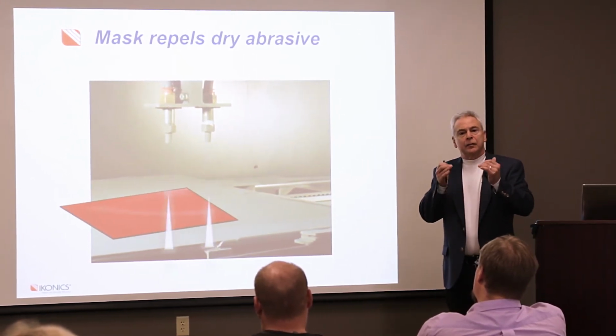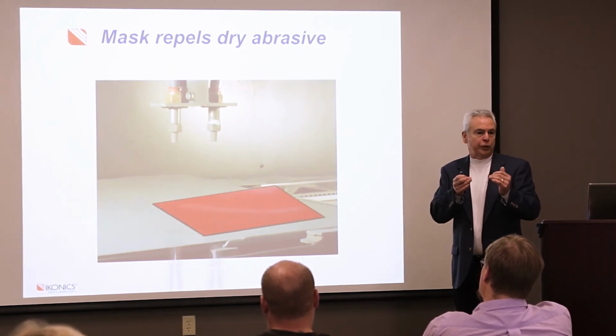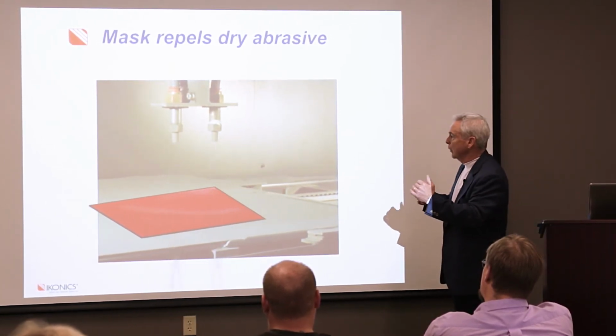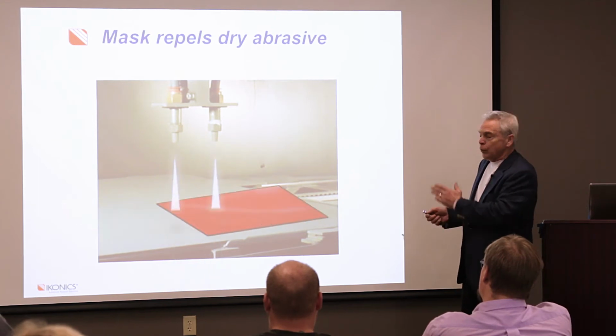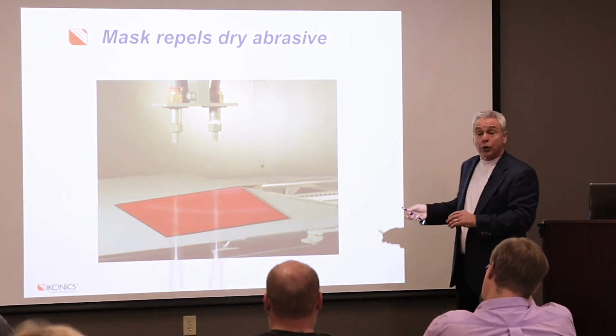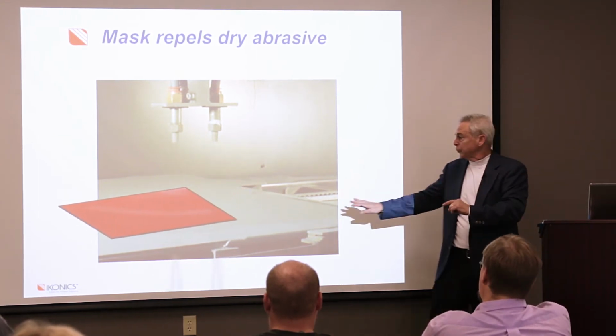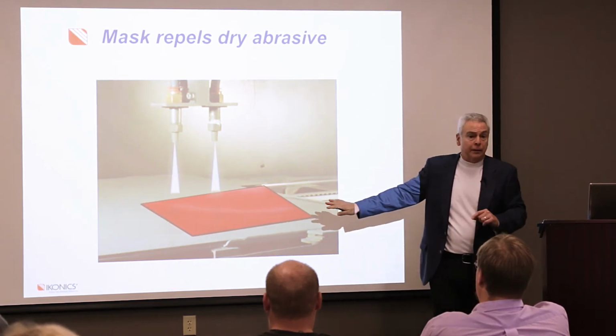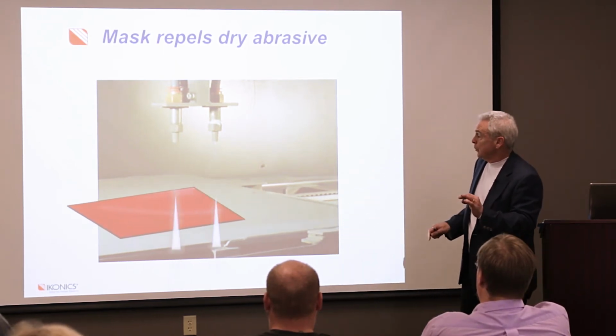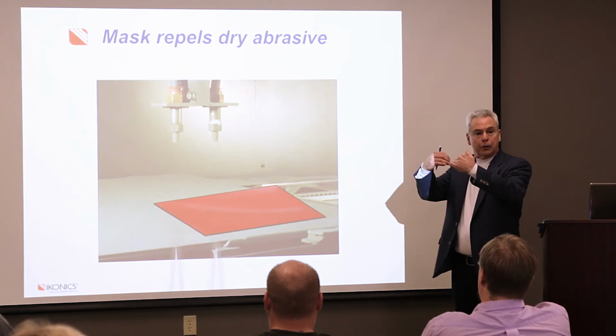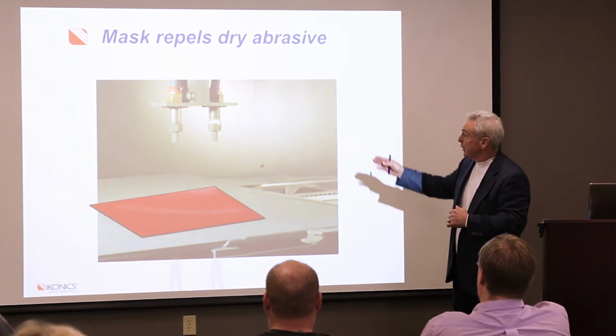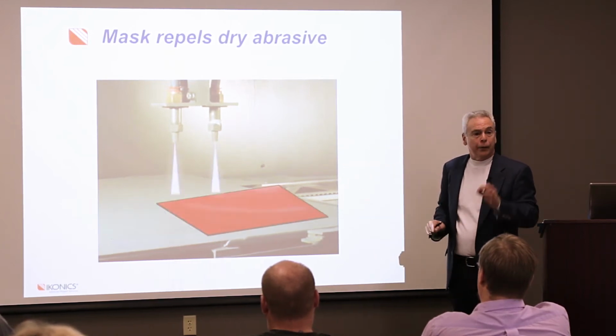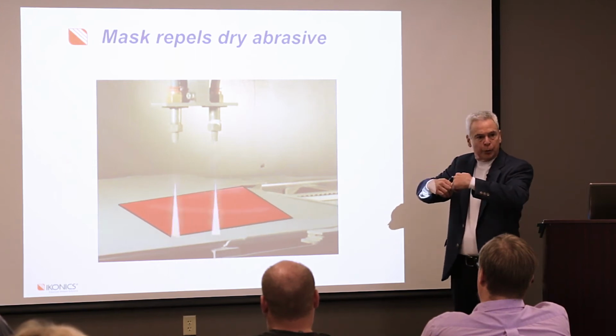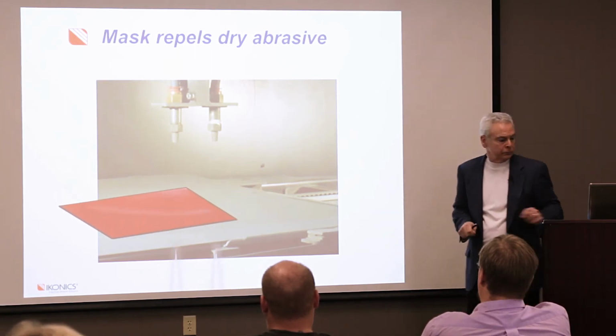And what you'll see here, we don't blast one hole at a time like you would typically drill one hole at a time or water jet one hole at a time. We do a scanning approach. So we're not imparting a lot of stress to this substrate while this process is going on. And that's a key point here. So what we're doing is we're gradually putting those holes through the substrate because the abrasive is going through the holes in the mask and starting to abrade away at the substrate.